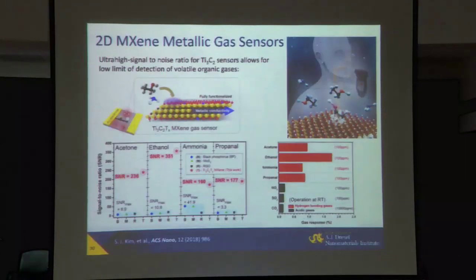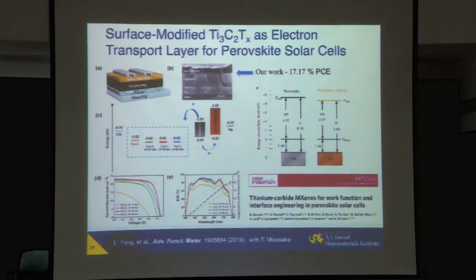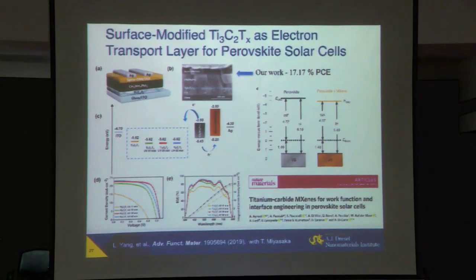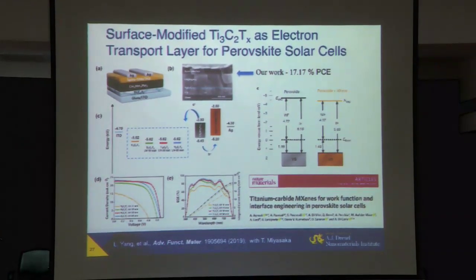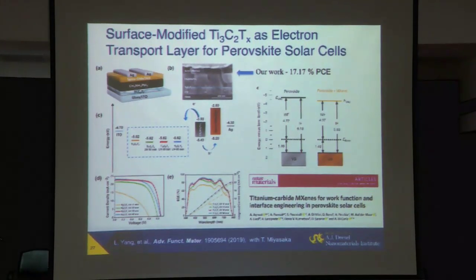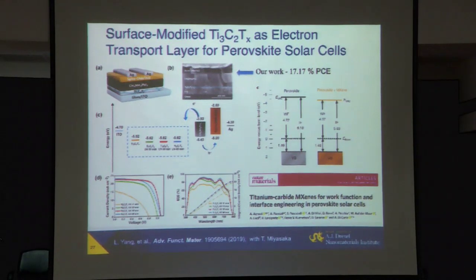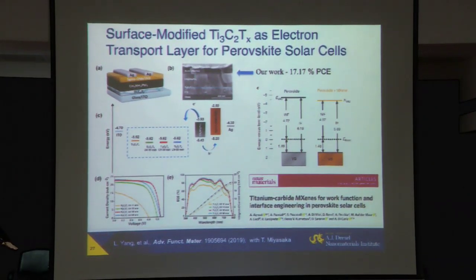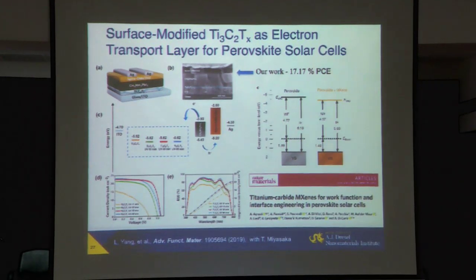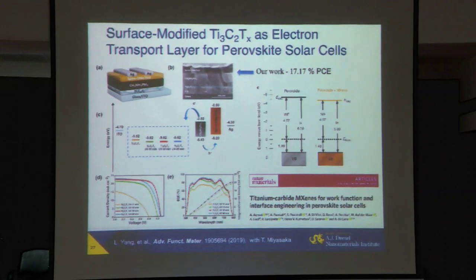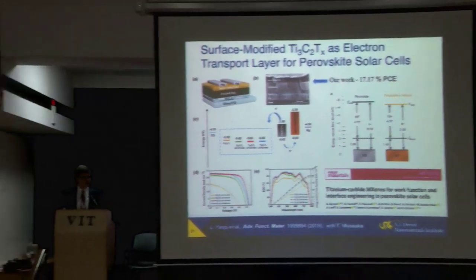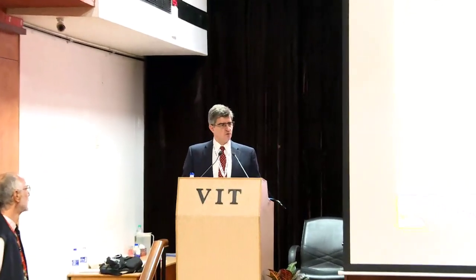But also, of course, you can change it permanently, and this was done in the case of solar cells, by changing surface chemistry. OH will actually take it to roughly probably minus 2, but fluorine can drop it down to minus 8. So basically, it's a lot. We cannot do it reversibly, at least we don't know how to do it reversibly, with fluorine, hydrogen, but oxygen is right in the middle, like minus 5. So in this range, it's pretty easy to tune by, for example, drying it, heating it, removing hydrogen from the surface, or we can get more fluorinated material by using HF. So this is a range we can play with. We published a paper in Chemistry of Materials, on tuning work function of MXenes, earlier this year.